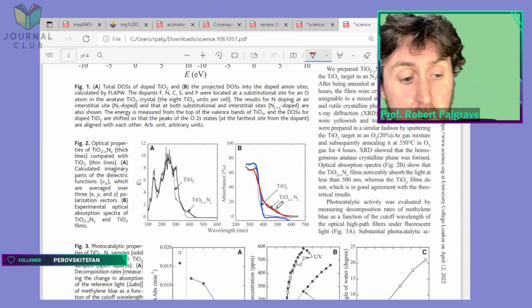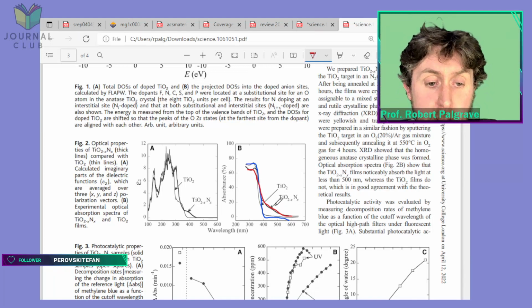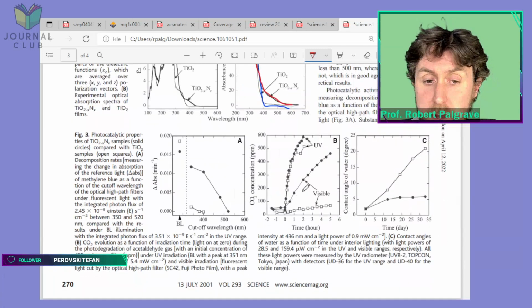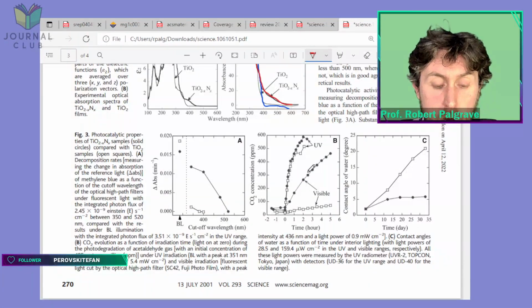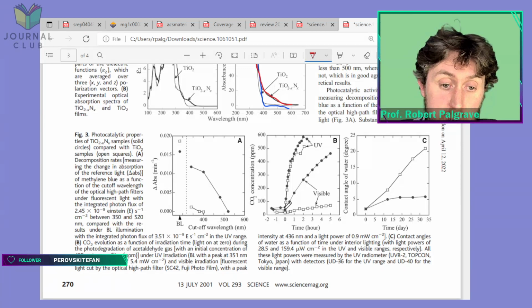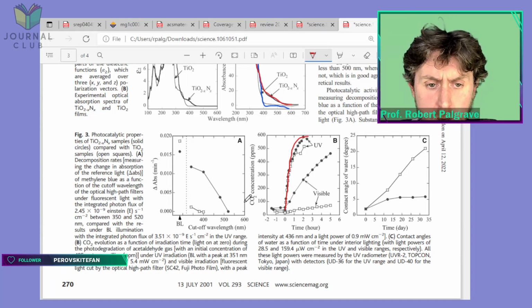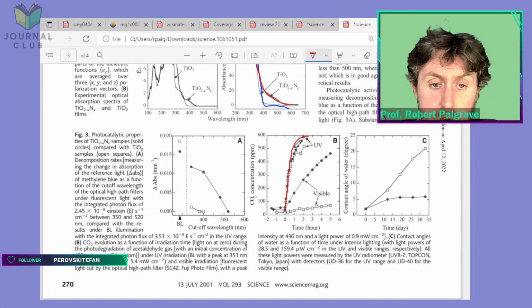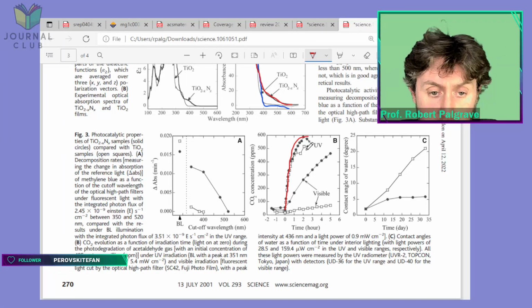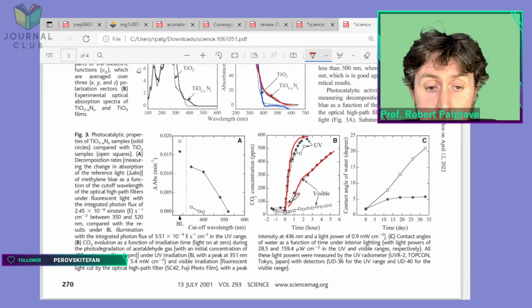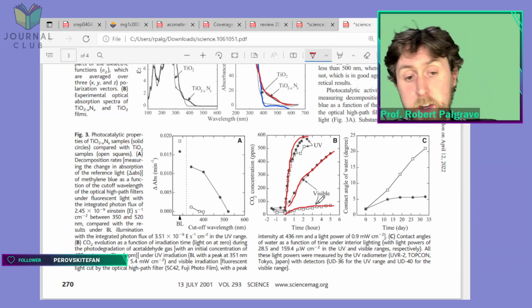So your nitrogen-doped TiO2 is absorbing that light in the visible region, and as they showed in this paper, it's actually able to do photocatalysis with that. So under UV light, the photocatalysis is better. They're measuring the photocatalysis by how much CO2 they're producing when they're destroying an organic pollutant, I think. So UV light is most effective, but the nitrogen-doped TiO2 is pretty effective in visible light. You get quite a lot of activity compared to the undoped TiO2, which doesn't really do anything in visible light.